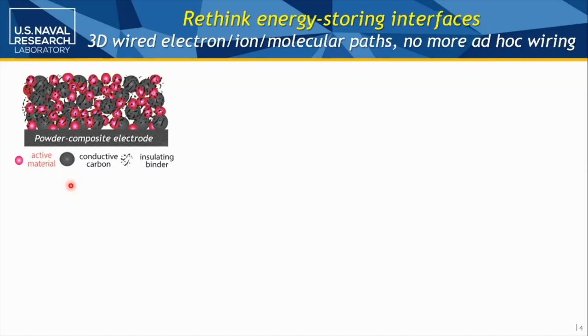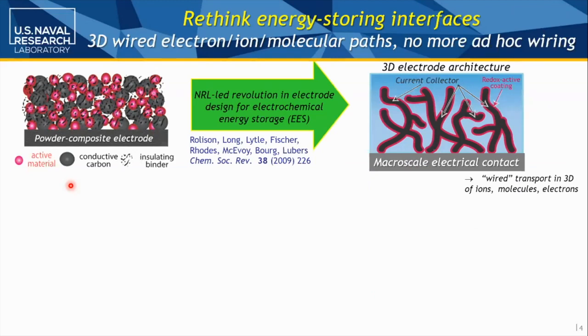So as we recognized what ruthenia as a pseudocapacitor was teaching us, we wanted to think about how do we wire electrons and ions. So we may still have a macro scale electrical contact, but we want, if you will, an architected volume where the current is always going to be able to go rapidly back to that macro scale contact, and some kind of modification of that, and ultimately filling up somewhat so you've got the active material quantity you need in terms of per gram of electrode or per square area if you're thinking of areal, and paths to move ions.